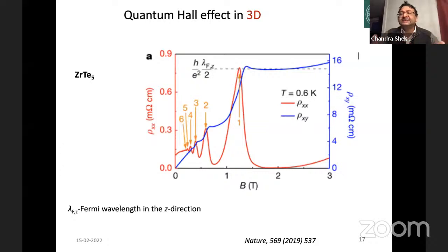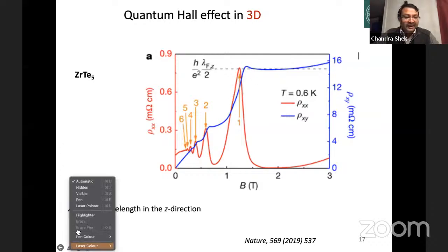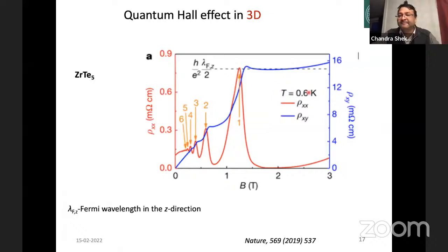When we change the dimensionality of the system, we change the whole property. It is well known that this quantization always occurs in low-dimensional systems and at low temperature, because this quantum phenomenon is always a low-energy phenomenon. Low energy means the temperature is always defined in terms of energy. So we can see this measurement at 0.6 Kelvin. When you go to higher temperature, all these step properties are gone.